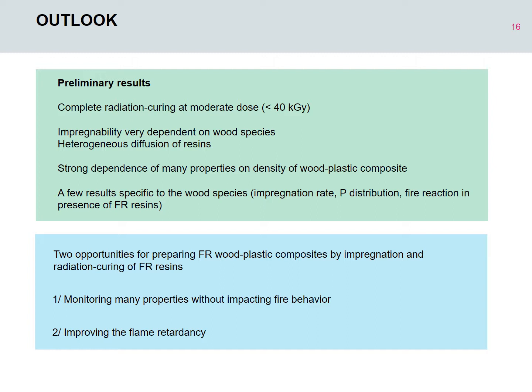We don't pretend that we obtain very good flame retarded materials, but we think our method is promising to reach two objectives. The first one would be to monitor some macroscopic properties by incorporating a resin, and by choosing a flame retarded resin, it would be possible to monitor these properties without deteriorating the fire behavior. And the second objective would be to improve clearly, significantly, the flame retardancy, but in that case, we need to use much more flame retarded resins, especially probably containing much higher phosphorus content.